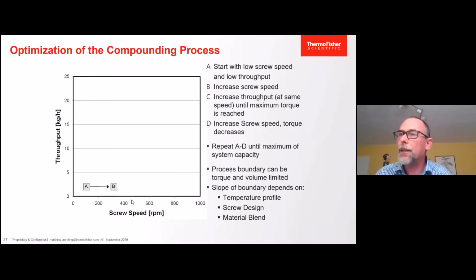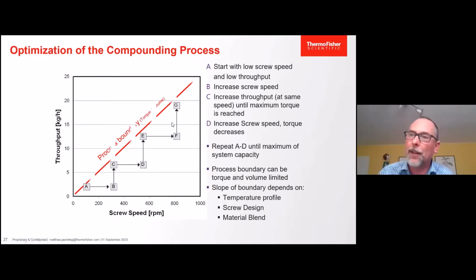We check the torque, and we can increase the screw speed, and then we can start to increase the throughput. So we change the set points for the feeder and give more material to the system. We see the torque will increase, and then we can speed up again. After that, increase feed rate, speed up again, increase feed rate. And once we keep our points below the process boundary, we will have a stable process. In this way, you can select different speed and throughput combinations which are useful for your material.